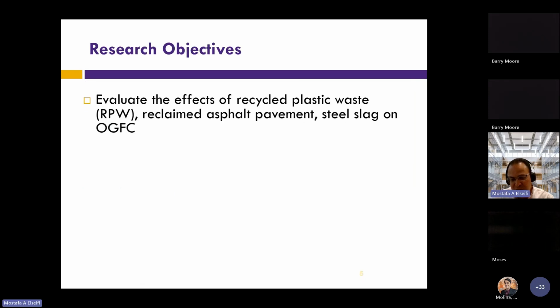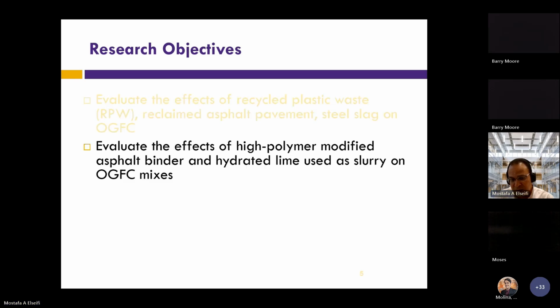So our objective was to look at innovative methods to reduce the cost while improving the performance of this mix. So we looked at the incorporation of recycled plastic waste, reclaimed asphalt pavement, and steel slag. We also looked at the use of high polymer modified asphalt binder and hydrated lime that we use as slurry in the mix. So again, as part of our state here, and I'm sure other states in the region, none of these additives are currently allowed or used in OGFC.